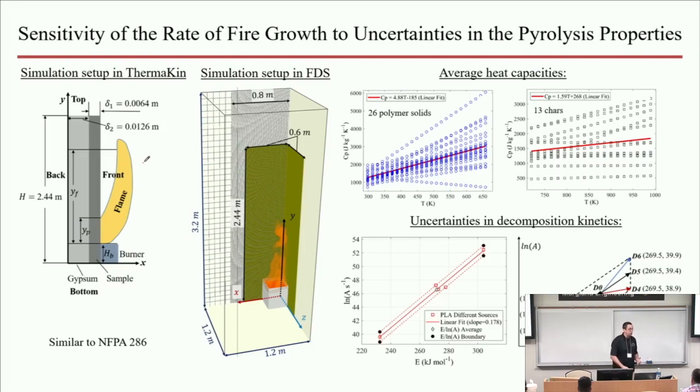Okay, so you do need this data over a range of temperatures, as much of a range as you can have. These measurements are impacted by the fact that at elevated temperatures, the material may go through some shape changes and other changes that may interfere with, for example, the thermal contact that we use in this measurement, and so on and so forth. So we do not measure this property sufficiently well, and partially we don't do it because it is a temperature-dependent property.